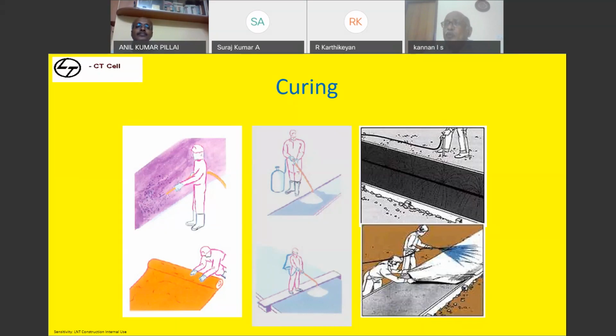Generally, people ask, if I have applied a water-based curing compound, whether I need to scrape the surface to do the activity. Nothing. When you're going with an acrylic base, you can continue, because all bonding can happen. Only wax is having an issue. Depending upon the surface and the shape of the element, you decide what type of curing is best for the structure. Ensure in the structures, internal water is kept. That's all.